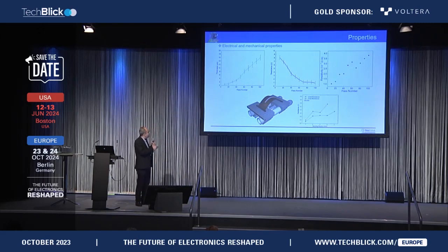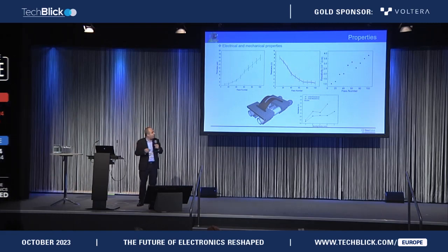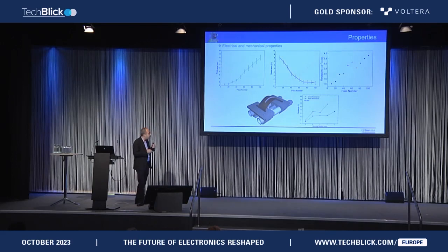And then we also study the resistance. Resistivity goes down to 10 to the minus 7 without optimization. We have not done any optimization yet, and we are already reaching 10 to the minus 7, which is quite impressive. We do, of course, bending tests, in this example up to 100,000 cycles. We also do up to a few million cycles, and nothing. We don't see significant changes in the resistivity of these lines that we print.